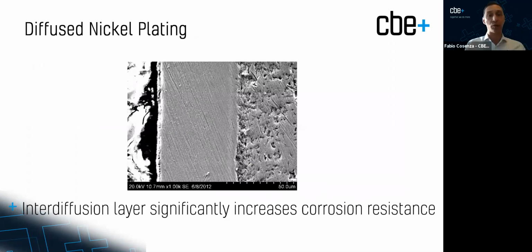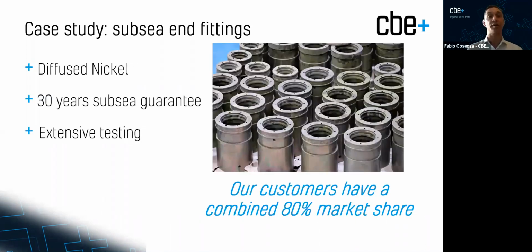We also carry out a process called diffuse nickel plating, where by heat treating the nickel plating, we create an interdiffusion layer. So you can see in this picture, on the right-hand side, we have our base metal. In the middle, we have the interdiffusion layer I was describing, and on the left, we have the external nickel plating. By interdiffusing nickel into the substrate, we create a molecular structure that, as you can see, is very compact and becomes a really strong barrier to corrosion resistance, pushing it even further than that of nickel plating as plated. So this is very helpful for our customers who manufacture subsea end fittings.